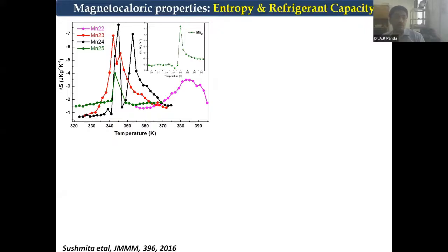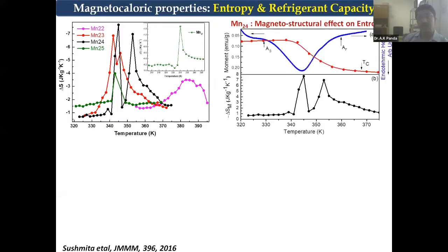Now these are the entropy plots for the alloy systems. What you find here is very interesting actually. Mn24, the manganese 24 atomic percent alloy, shows quite a high delta S, and that comes intermediately with 23, and this is the magnetostructural effect on entropy. What you find is the endothermic heat flow and the entropy change. We are plotting the entropy change with respect to the DSC temperature. So you find that it is more or less overlapping with the peak entropy.